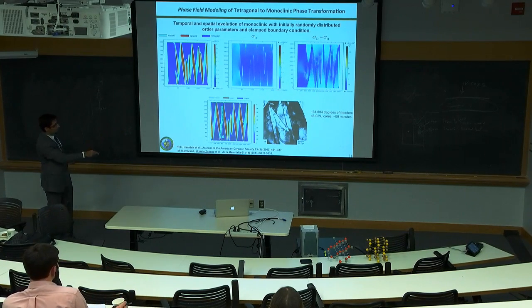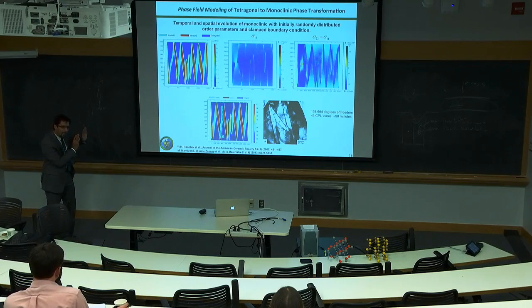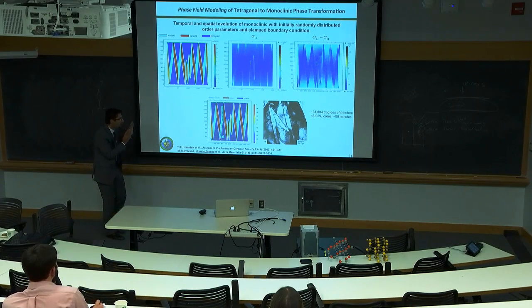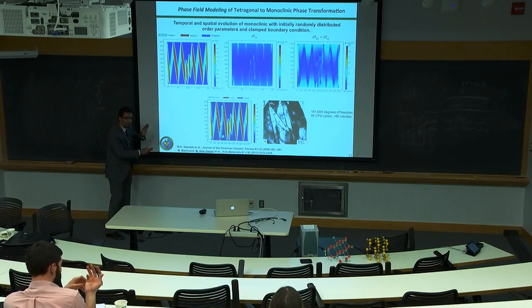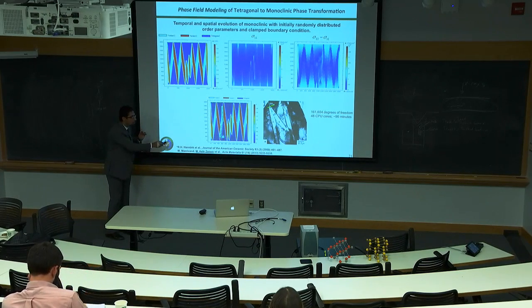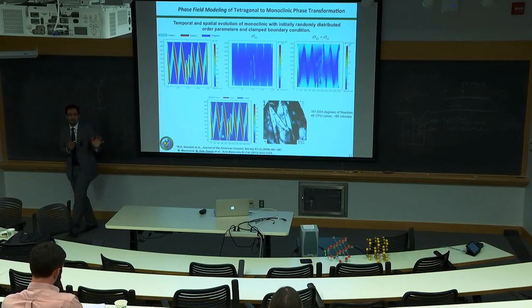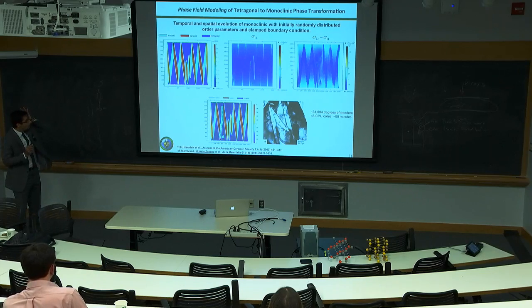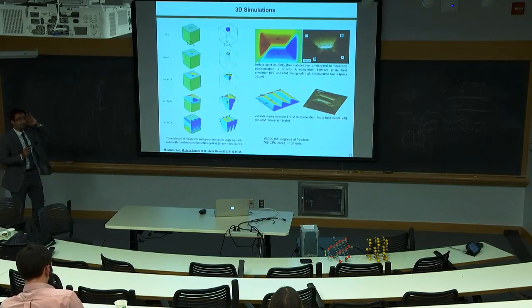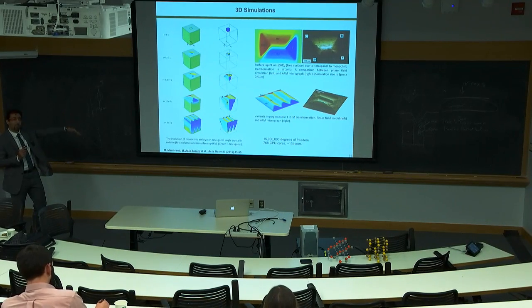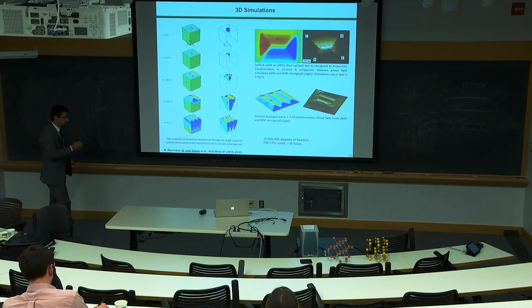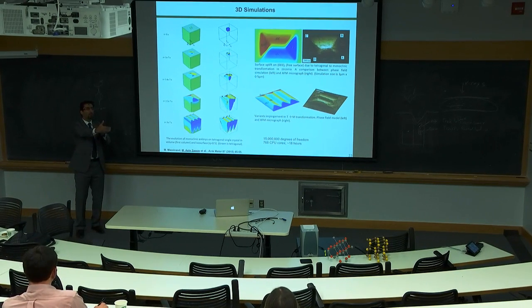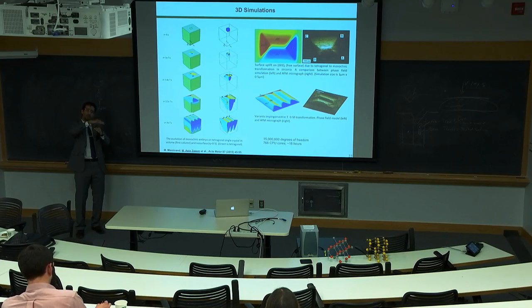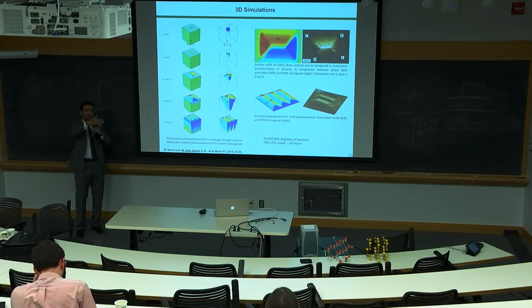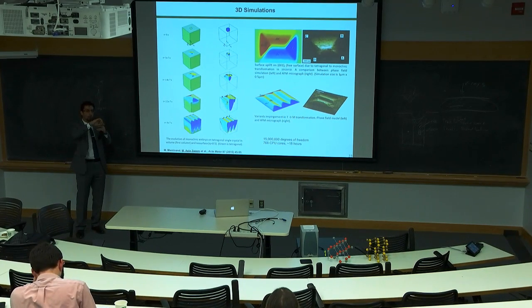And these are stress fields. And we quantitatively validated our simulation. We measured the size, the distance, the volume fraction, compared it to experiments. So these are quantitative models. What else we did? We ran three-dimensional simulations for free surfaces. Why? Because cladding is in contact with water. So that surface can mechanically corrugate or deform.